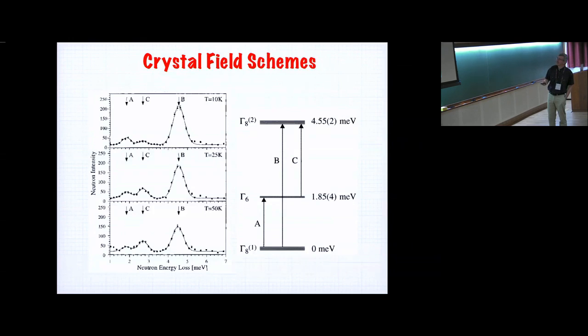A down here is from the ground state up, but C in the middle is from the first excited state to the second, and you see its temperature dependence is not obvious like the other two. That's because thermal energy is used to populate this before you can excite it up. So at the lowest temperatures, this peak C would vanish completely.